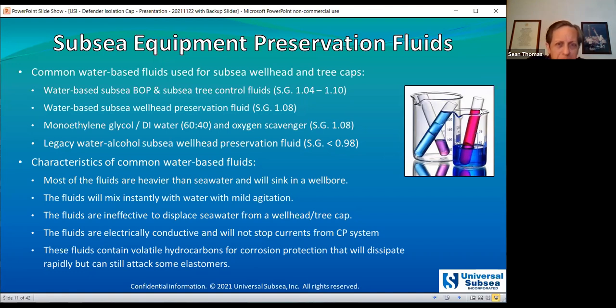So the characteristics of the majority of these fluids are heavier than seawater, and they're water-based. They'll typically tend to sink in a well bore. And these fluids will instantly mix with water if you have any significant agitation. And the one significant thing is being water-based, generally ineffective to actually displace the seawater from inside a cap or the upper bore of the wellhead or tree. Fluids are also electrically conductive, so they won't act as a barrier to the electrical currents from the CP system. Many of these fluids contain volatile hydrocarbons that provide the corrosion protection. Those hydrocarbons will dissipate pretty quickly, and there are known examples where the hydrocarbon additives attacked elastomers.